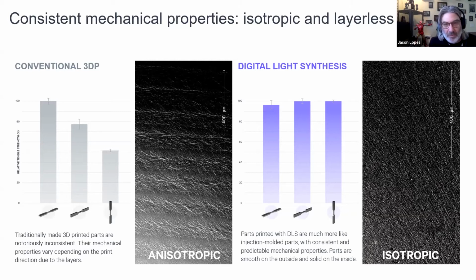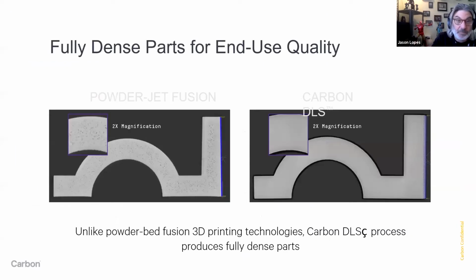Well, if you look at digital light synthesis, we've taken orientation really out of the equation. X, Y, and Z will give you full properties. And if you look at one of our parts under a 400 micron scope as well, you'll see the isotropic properties right there. It has a grain structure very similar to an injection molded part. So once again, if you look at us compared to a powder-based technology under 2x magnification, you can actually see the porosity inside of the part. In the digital light synthesis part, you can actually see the isotropic properties.